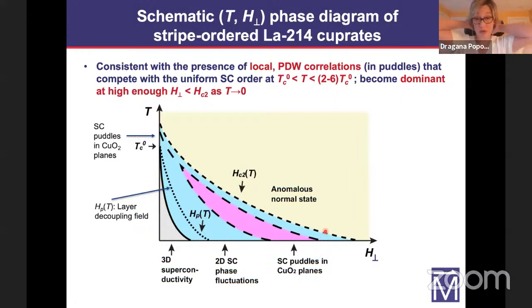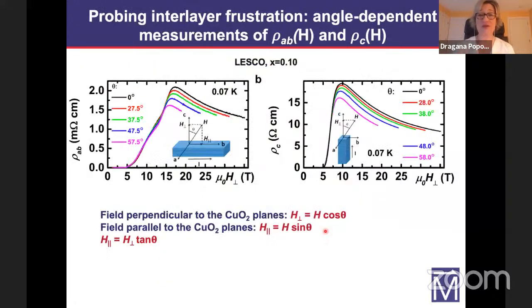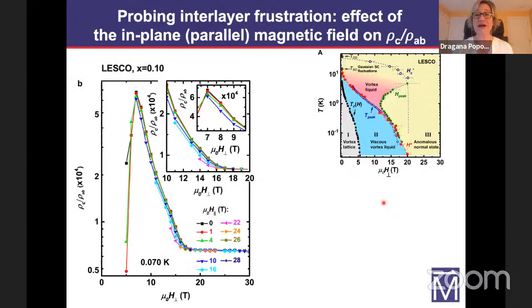So the data are consistent with the pair density wave picture, but the true test really is the application of a suitable perturbation of an in-plane magnetic field, which within the pair density wave picture should frustrate the interlayer Josephson coupling, reduce the frustration and reduce the anisotropy. So in practice, what we do is we rotate the sample in the magnetic field, and from the total field applied and the angle, we can calculate the perpendicular and parallel field components, and we can extract the values of the in-plane and out-of-plane resistivities for a particular combination of perpendicular and parallel fields. So what we want to do is look at the anisotropy as a function of, first, the perpendicular field. In other words, we want to see what it's like in different parts of this vortex phase diagram, which is what is shown here at a fixed temperature. So we are going this way.